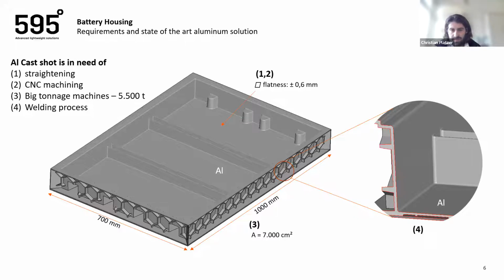And to achieve this flatness, usually the aluminum die casters have to mill the complete inner surface of the housing, and also the backside, because the backside, number 4, is being covered by an aluminum sheet that you need to weld on the bottom. And before you can weld it, you also need to machine that surface. At least this is what we hear talking to many companies that are doing this.